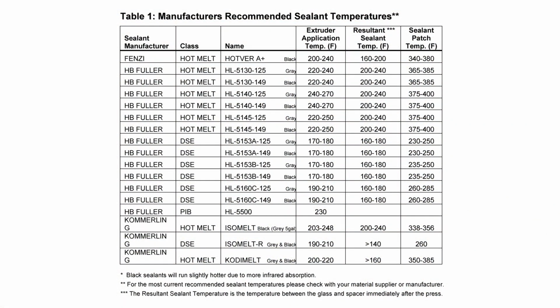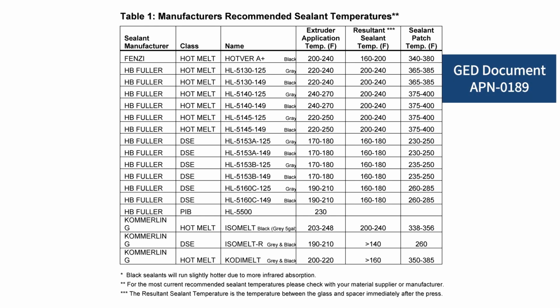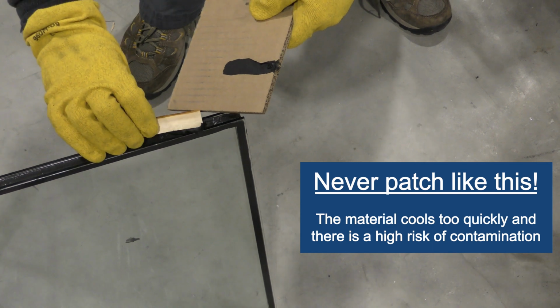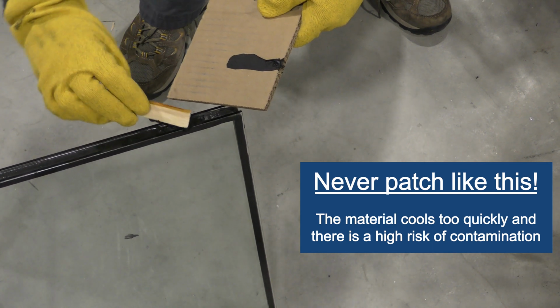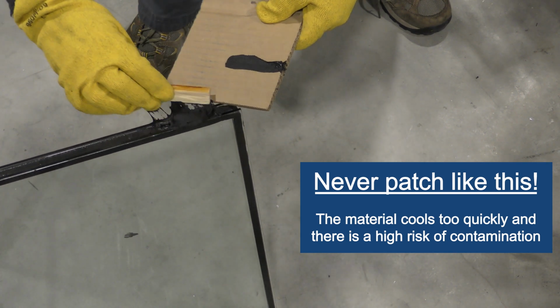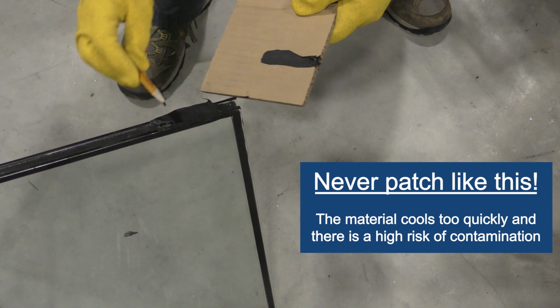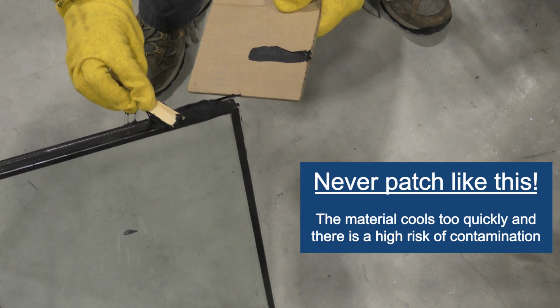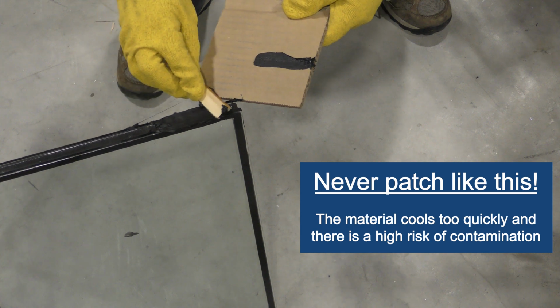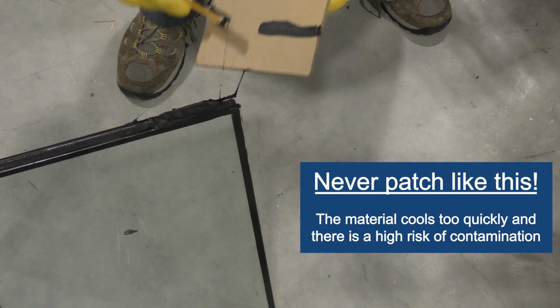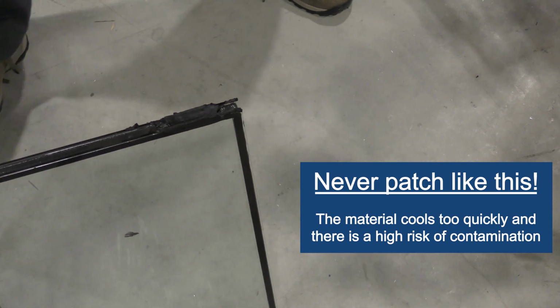Many of these materials and their manufacturer's recommended extrusion, oven, and patch pump temperatures are listed in GED document APN 0189. Do not use sealant gathered from other sources other than the dispensing gun, such as from the pump bleeder or platen. This material will not be hot enough to remelt the sealant on the IG unit and can also easily be contaminated with dust or other debris.